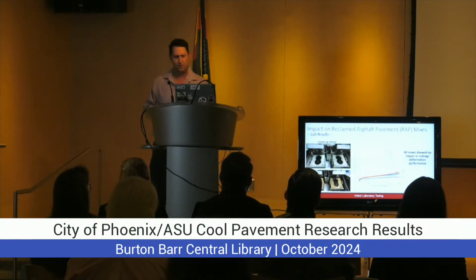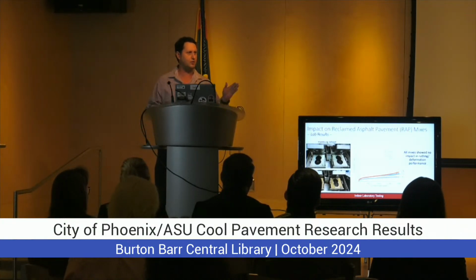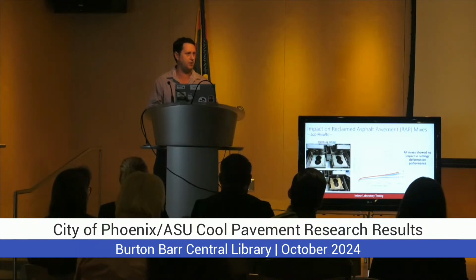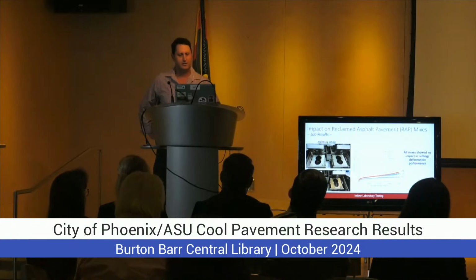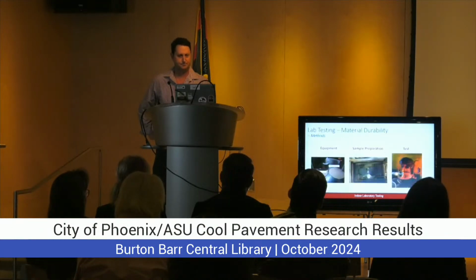And then the other test that we performed is called the Hamburg wheel. Basically, we place the samples and we have a wheel going back and forth 20,000 times. And usually we have a threshold line of half an inch. All of the products that we tested were way below the threshold line that we use as a specification or as a measure. So again, going back to the 3 tests that we did, there is no concern about using these materials in the future for RAP mixes.